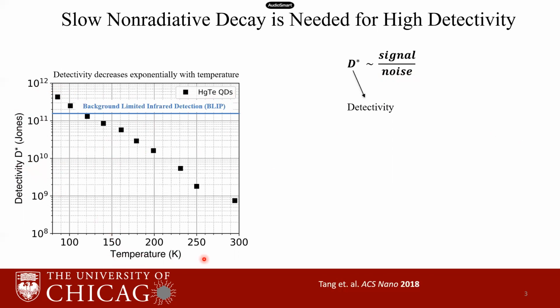And here we have the temperature on the x-axis. We can see that the detectivity decreases exponentially as the temperature is increased. And this is because the noise increases due to thermal recombination. The ideal detectivity goal is this horizontal line near 10 to the 11, and this is called background limited infrared detection, or BLIP. We can achieve background limited detection around 120 Kelvin, but this is not an option for cameras because this makes them bulky and expensive.